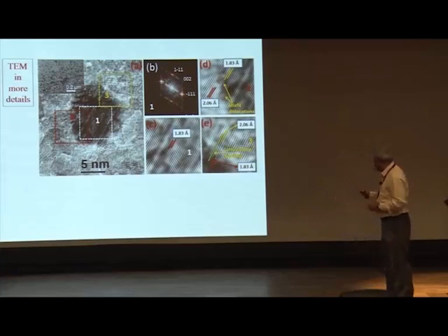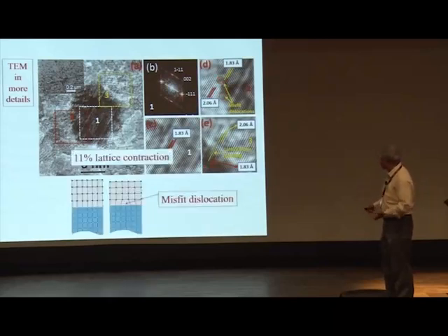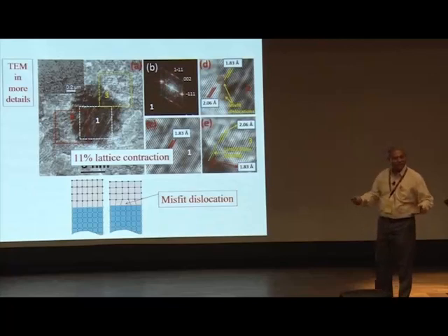And if you look at this other grain boundary also, this one, you see this. This is the lattice parameter. Here is 1.83, 2.06, but lattice planes are bent. That is to adapt to different lattice constants. If you look at this one, you see the dislocations here. This is a familiar situation for people who work in epitaxial growth.